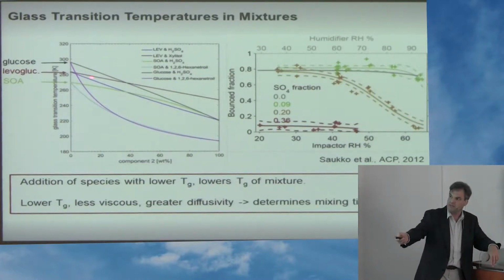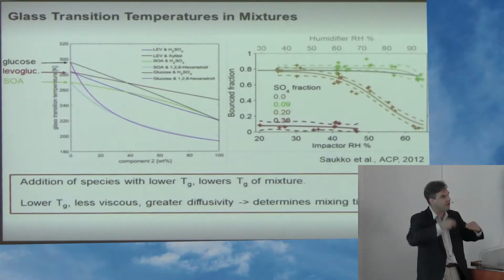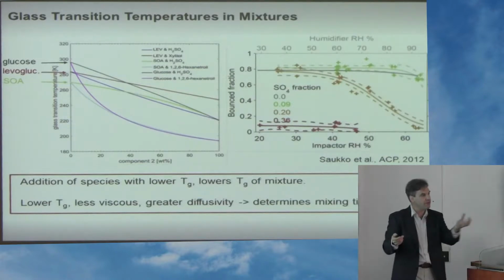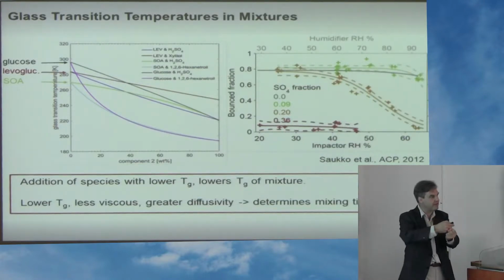But if I mix, and now look here at the black one and blue one, if I mix sulfates in, sulfuric acid, I can dramatically change the point when these particles become solid or liquid. And that means if a biomass burning plume comes over Mexico and takes up sulfates, the thermodynamic conditions when the phases change.